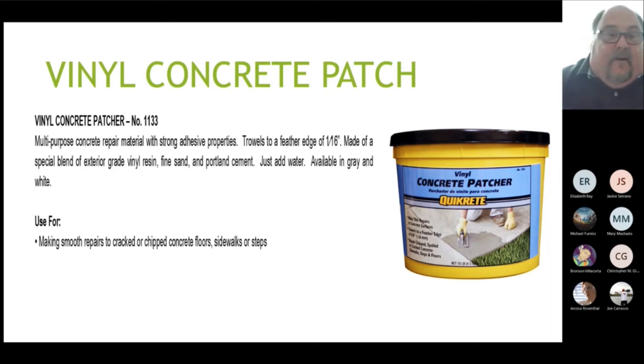The product itself is like 5,000 PSI, but the bond strength's incredible. So being able to go down to a feather edge, you can make those little ramps and transitions, or repair thin chips and pop outs. So you won't have to worry about it chipping up and popping up as things are rolling over, even things like pallet jacks. So it also works great for repairing cracks.